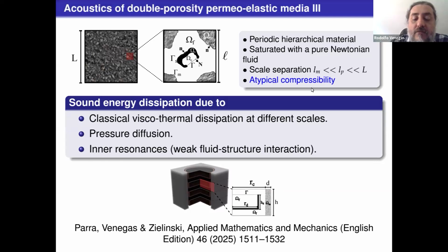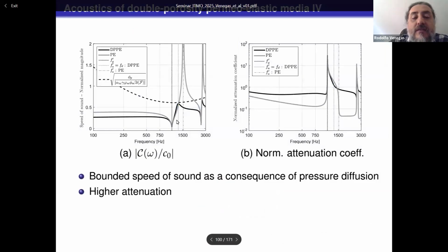Now, instead of having a plate that doesn't actually make the fluid phase disconnected, we can disconnect this fluid phase by creating a cavity that is closed by this plate in this way. So in that case, now we have an atypical compressibility. It's no longer an atypical permeability or dynamic density, and the effect can be seen here. If we have a double porosity permeoelastic material, the magnitude of the speed of sound is bounded, as shown here by this expression that depends on the imaginary part of this pressure diffusion function, and we have higher attenuation pretty much in the whole frequency range.